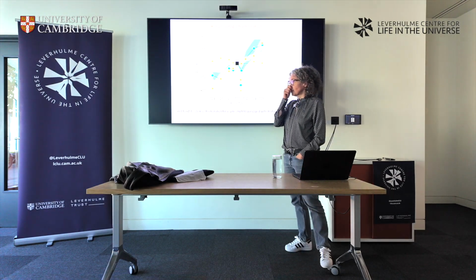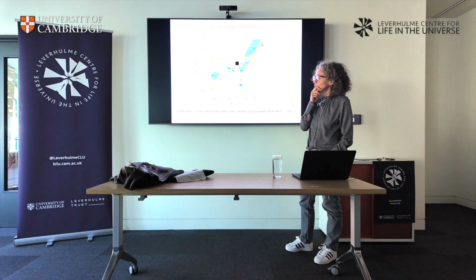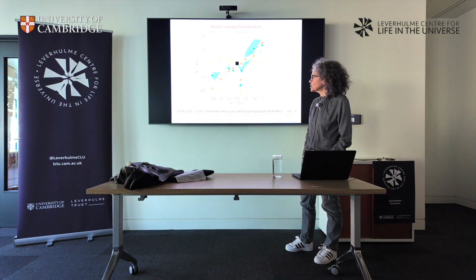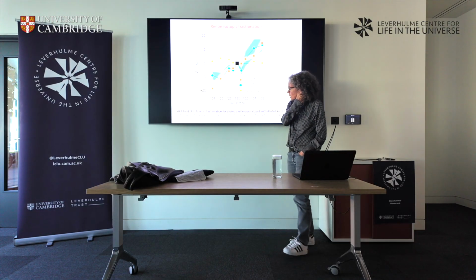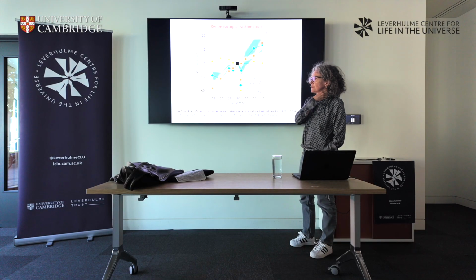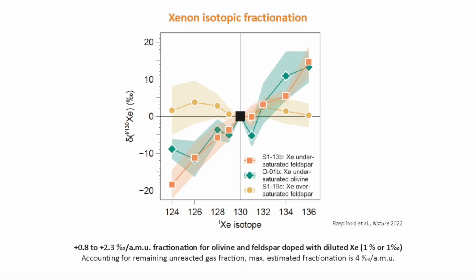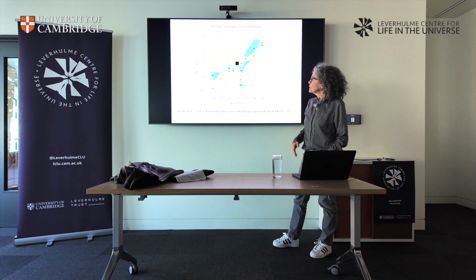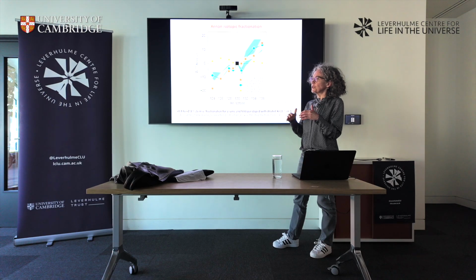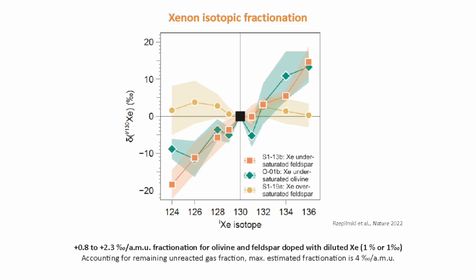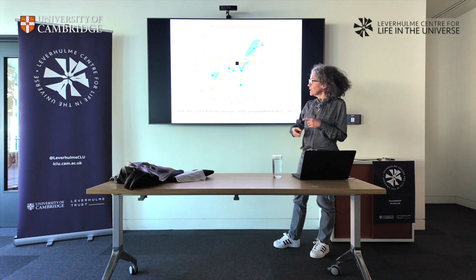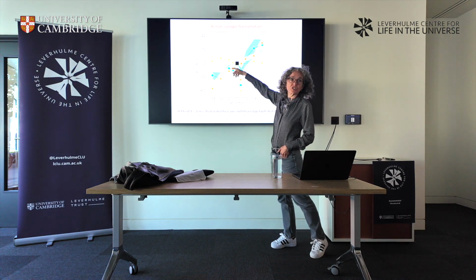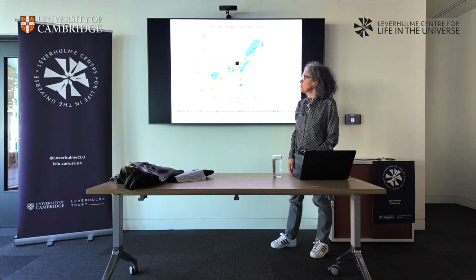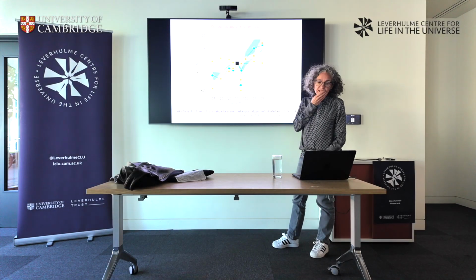So the next step was to measure isotopes on our samples. For this, you need to have a little bit more sample. We did large volume experiments. We did olivine, we did feldspars, and we sent the samples to nuclear isotope groups in France. We did observe, for the feldspar the orange square, for olivine the green symbols. And if we dope our sample with pure xenon gas, we don't see anything. That's this circle. If we dope the sample with a very diluted gas, with only 1% or 1 per mil xenon in it, then we see the fractionation. And so we have a mass fractionation of about 2 per mil per atomic mass unit. Okay, so we saw this.